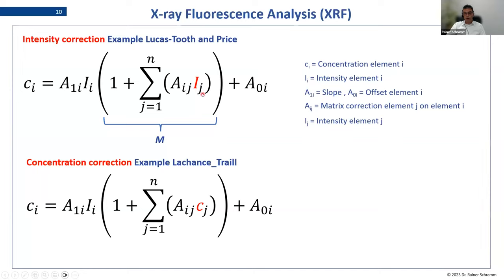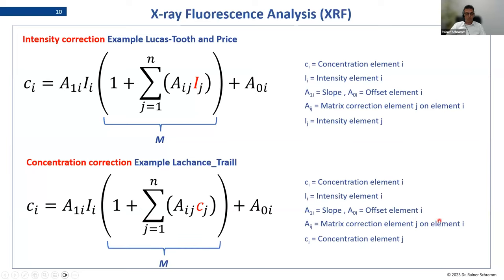I would always prefer a concentration-based correction model, because the matrix effects are already included, while an intensity-based model is just without any matrix correction for the other elements. It has, however, the advantage that you don't need to calibrate every element. So you could use other elements where you just know the intensity but no concentration, and you still can use them for matrix correction of the element of interest. But again, all this is based on standard samples, and you have to make sure that your standard samples are representing these effects, so that the mathematics are able to calculate the coefficients.